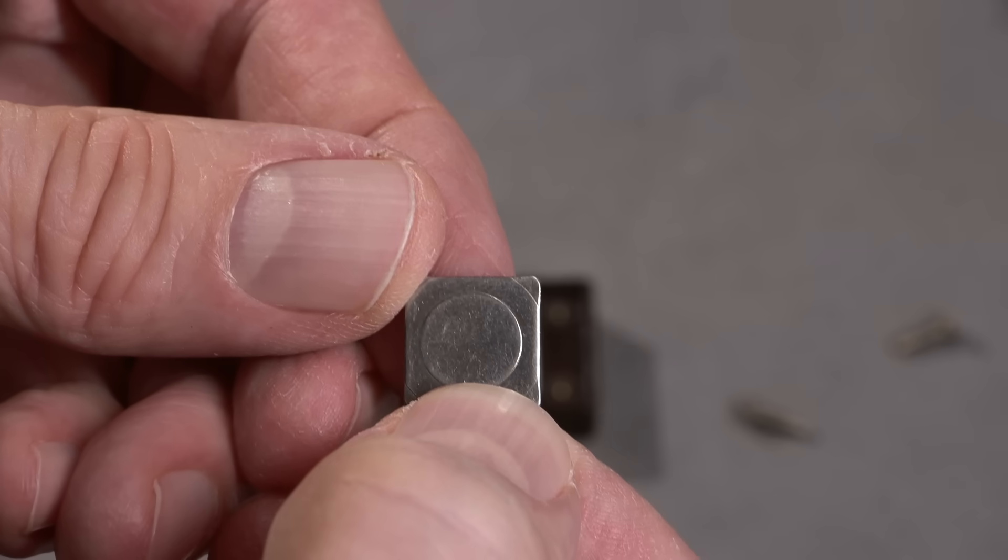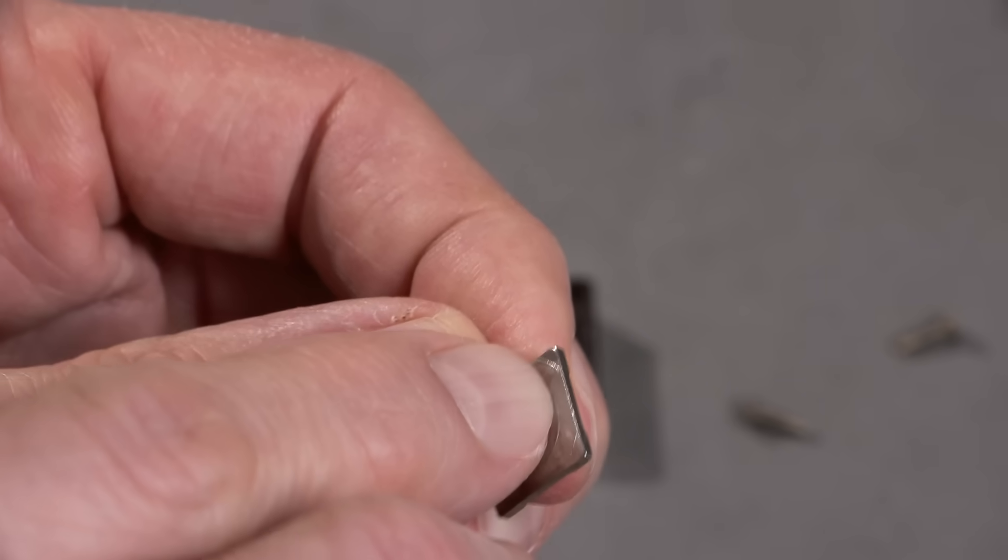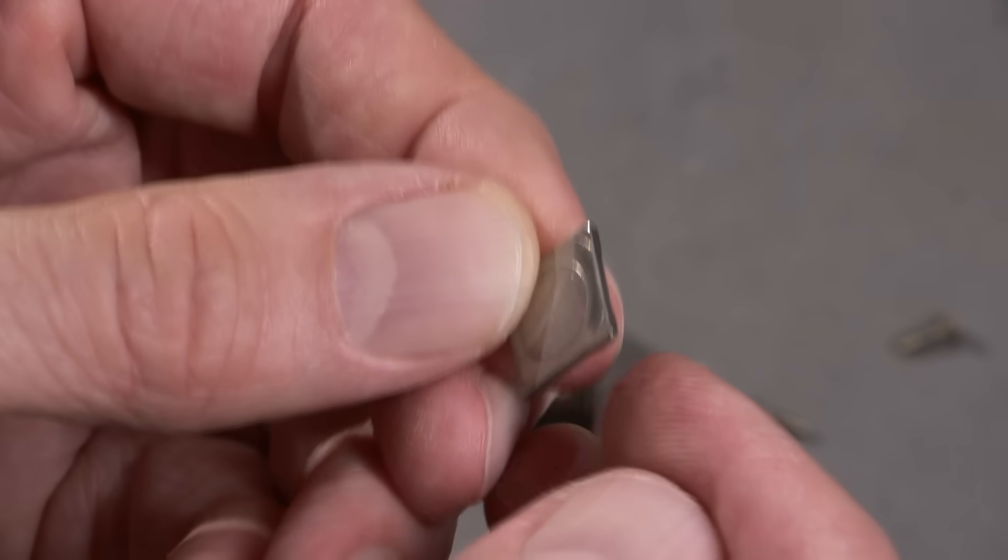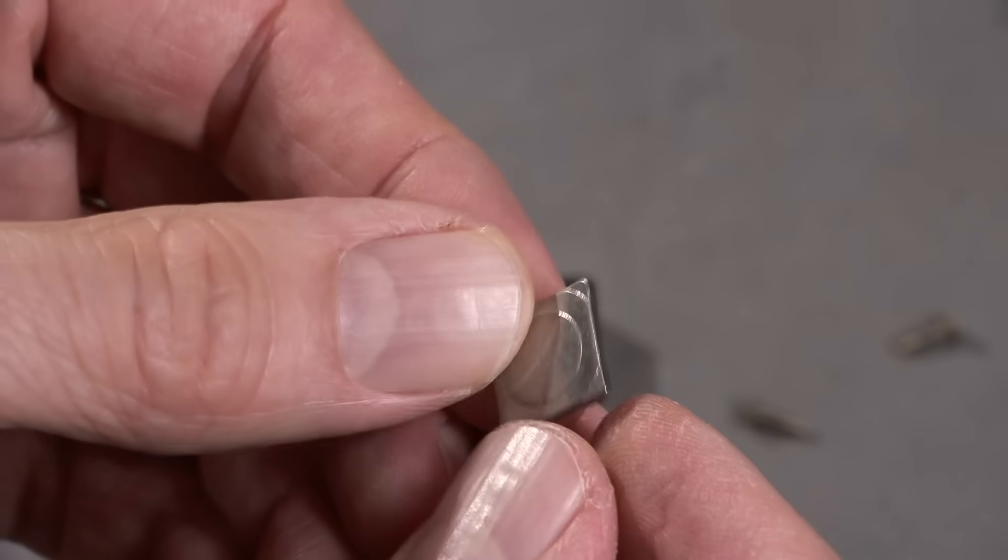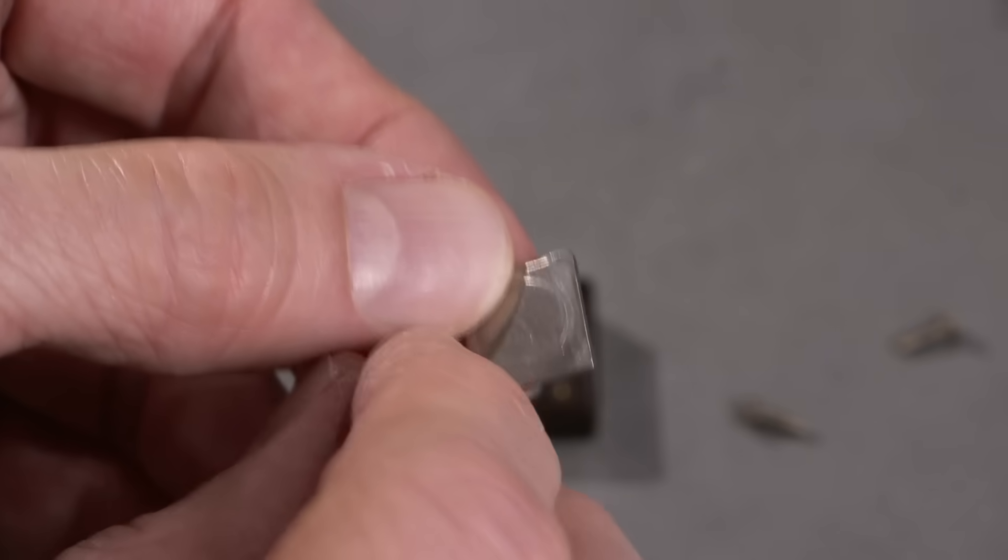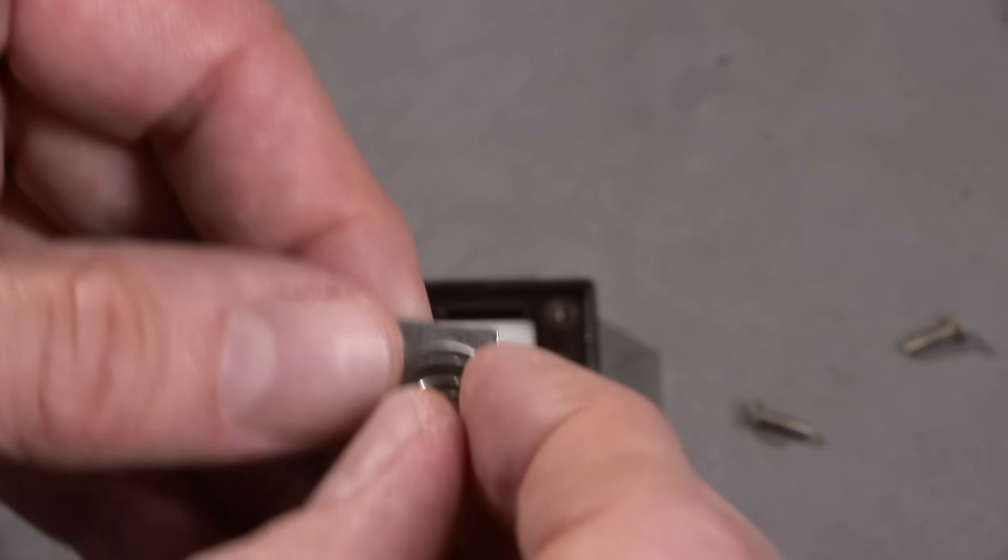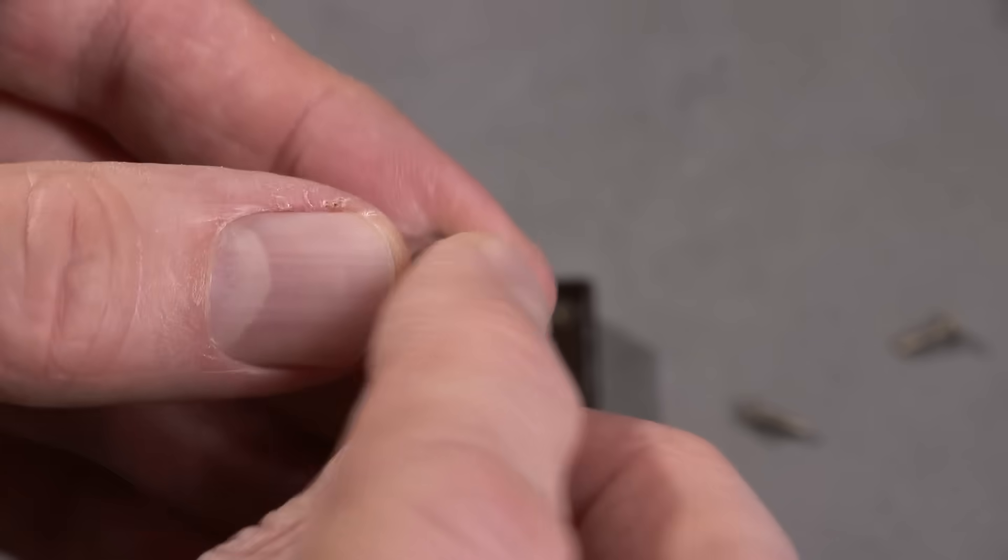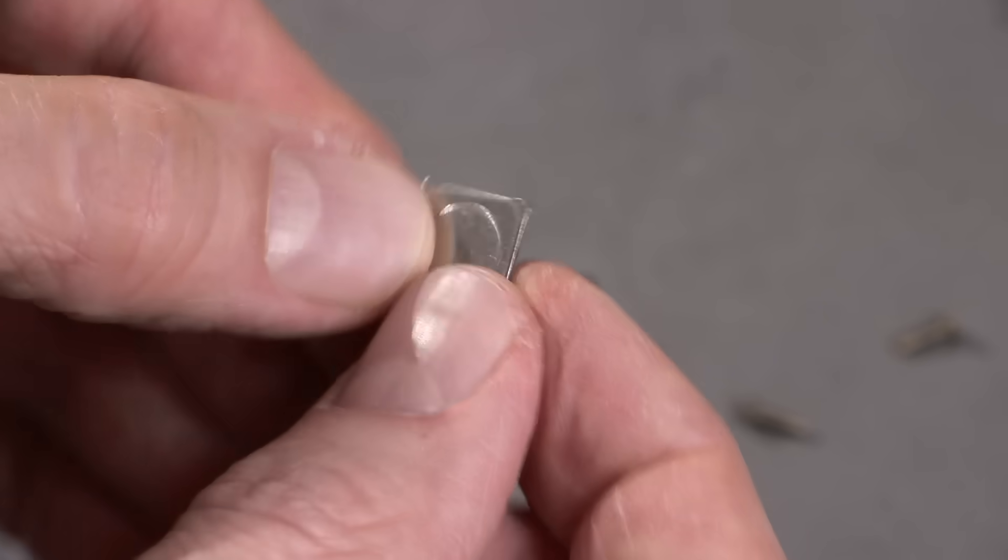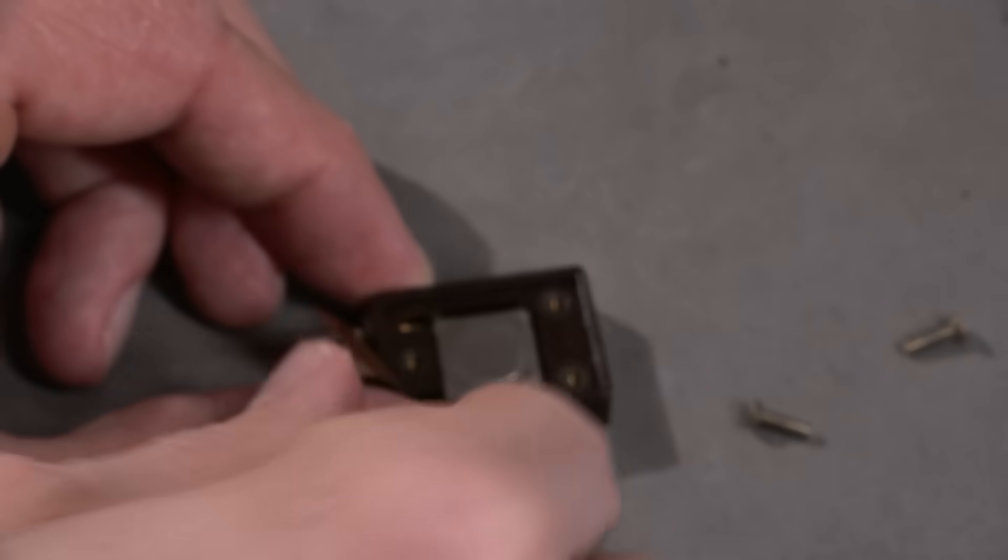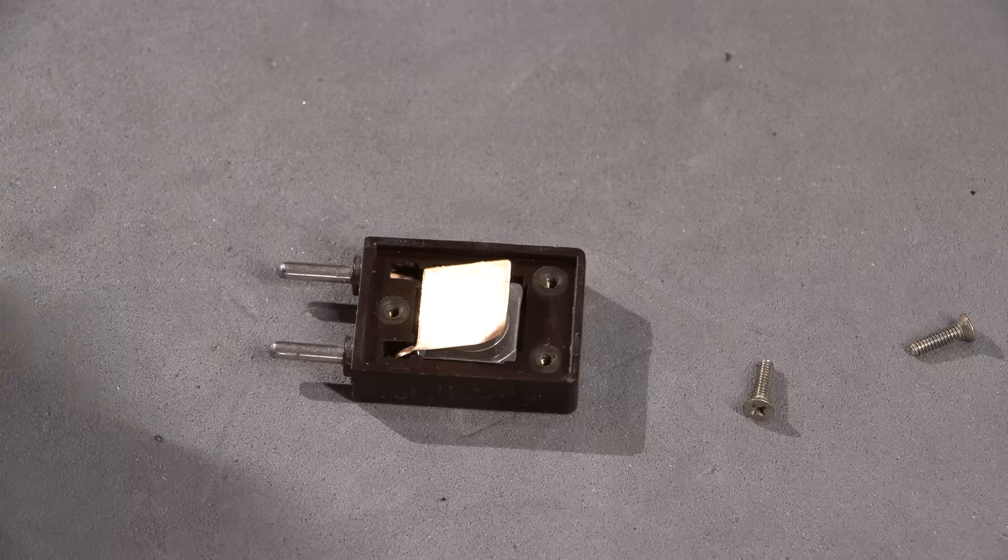This is the side that's going to face the crystal element, and that would be the back side, because this is lifted. If you were to put spring tension on this side, it would crack - the corners might crack because the spring itself is going to be out there. So it has to be put in the correct way. Putting this in backwards with that kind of spring tension would probably crack the crystal, so you got to be very careful with that.